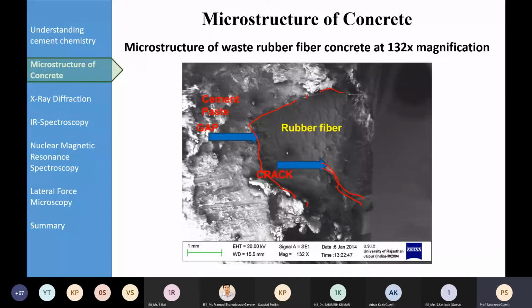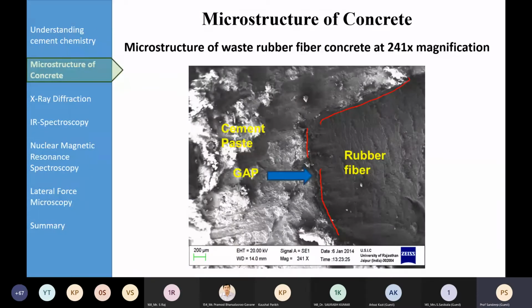of the concrete. And this cement paste gap, if you compare at the same magnification levels, is slightly less than that of rubber ash concrete. That means the properties will be slightly better than the rubber ash concrete. So if you have to use waste rubber tire, then we should use it in the form of rubber fiber rather than in the form of rubber ash. So you can see again here, it's quite visible, the rubber fiber and this gap between the cement paste and rubber fiber.